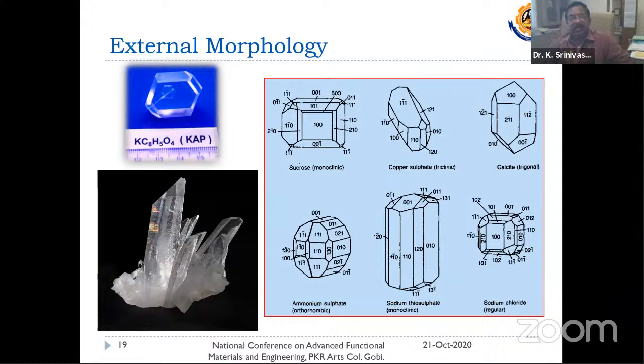When you measure a property along one particular direction, one particular plane, that will vary with respect to another plane. And also, the crystals could grow along different directions with different velocities. That's why it ends up with different kinds of morphologies. The fast growing face will lose its morphological significance. The slow growing face will exist with a large morphological importance. So in this way, there is an anisotropy in the growth velocity of single crystals along different crystallographic directions as well. That's why we end up with different morphologies.